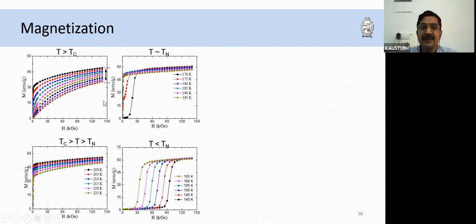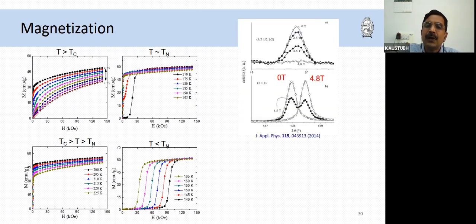And below TN, or very close to TN, the antiferromagnetic ground state can be converted to a ferromagnetic ground state under the application of a magnetic field. And in fact, it has been shown that even at 5 Kelvin, a 20 Tesla field can convert the antiferromagnetic state to a ferromagnetic state. So neutron diffraction was done on these materials by our collaborators in Germany, and they found that this field-induced transition is also a first-order transition.